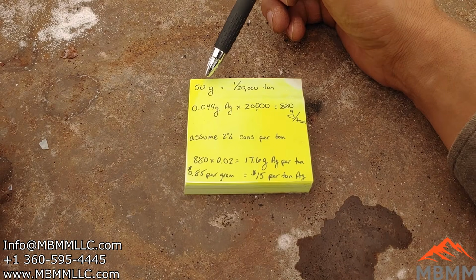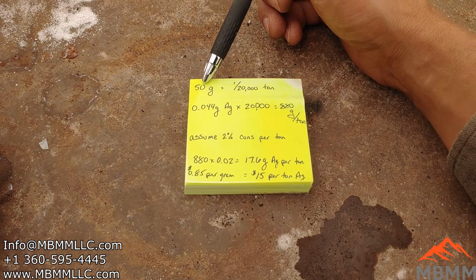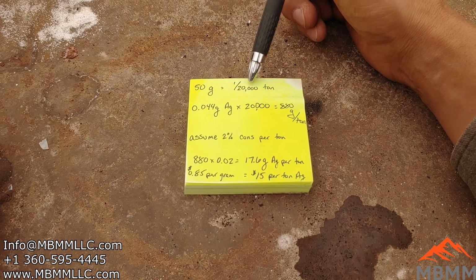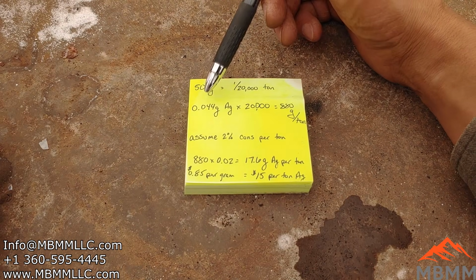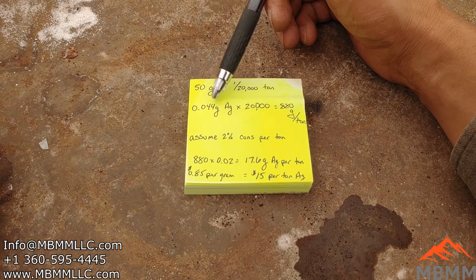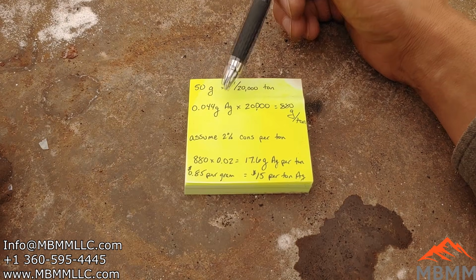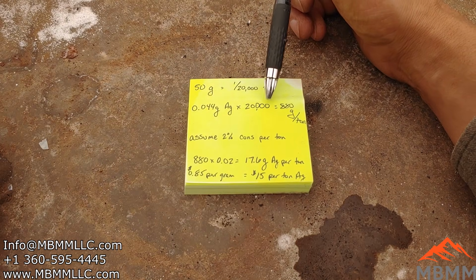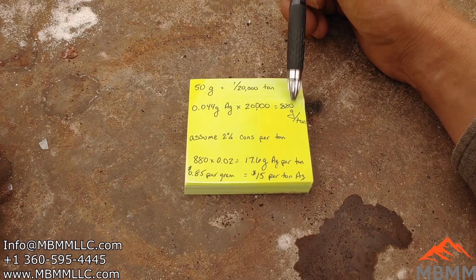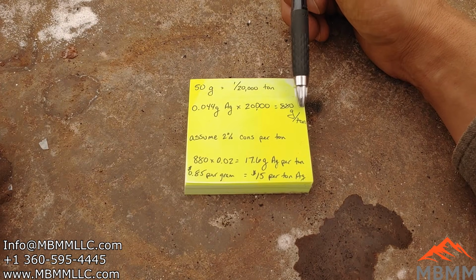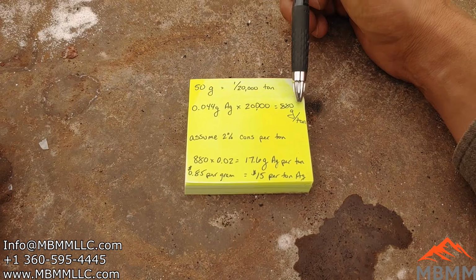All right, guys, so we do a little bit of math here. We ended up with a 50-gram sample, which is 1/20,000th of a ton. And out of that 50 grams, we ended up with 0.044 grams of silver. So you've got to multiply that by 20,000 to get grams per ton. So 880 grams per ton in the concentrates. That's not how much was in the ore originally. That was in the concentrates.